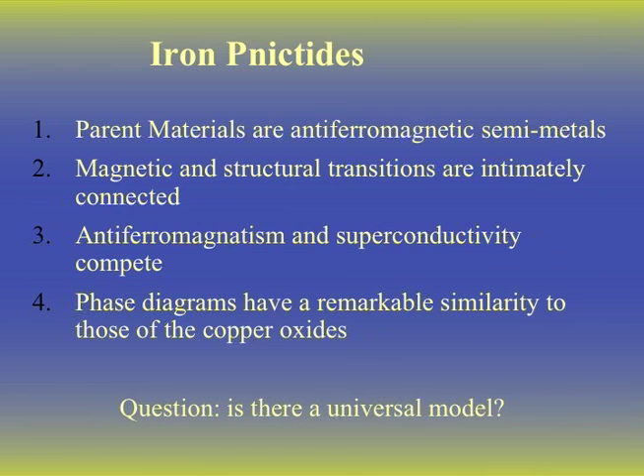So this then leads to a question, which is that for those of us who have been working on the microscopic details of the copper oxides, focusing on copper oxygen charge transfer, et cetera, whether or not we were seeing the trees and not the forest, and raises the issue of whether or not there is a universal model for these highly correlated electron systems in which the details are remarkably unimportant, but in which the essential feature is that you have competing antiferromagnetic and superconducting phases.